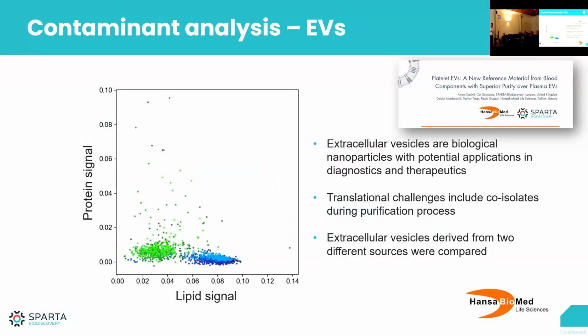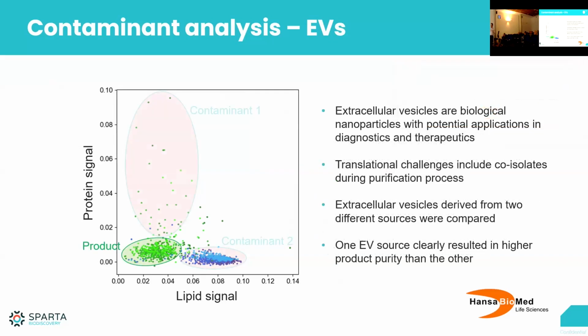Then another key thing, especially as we move towards more industry applications, is different contaminants in the sample. This was a study that we did with Hansa Biomed on extracellular vesicles. They had different isolations of the extracellular vesicles to use in different processes. What we can see here is that there were actually two different kinds of contaminants in the product population: a protein contaminant and a lipid contaminant, which was mainly lipoprotein particles, because these were blood-based isolates. We can see this distinction purely on a label-free Raman spectrum. We can see the compositional profiles of these particles being very different, and we can quantify the percentage of particles that have different compositions.